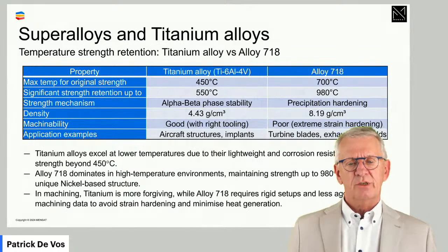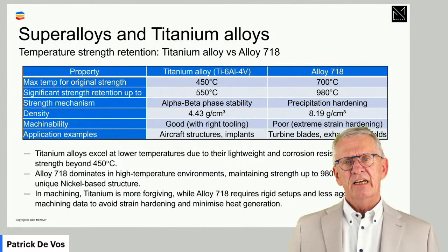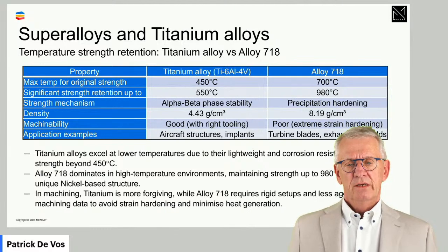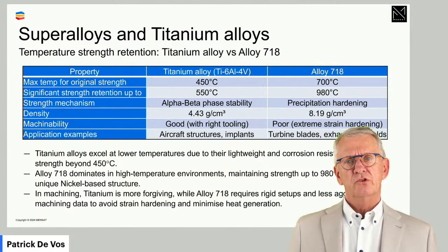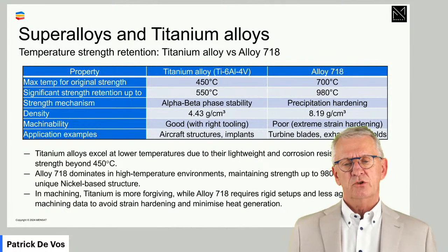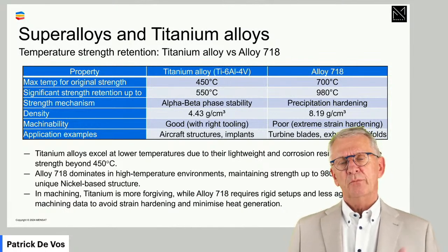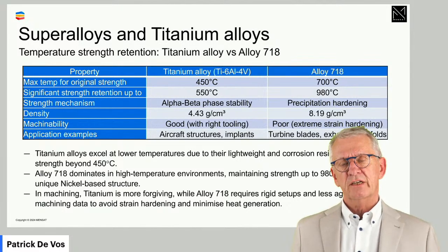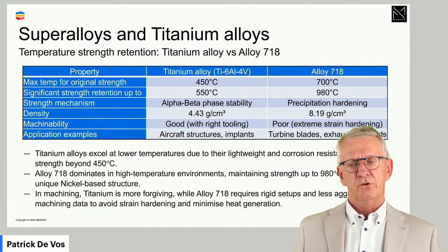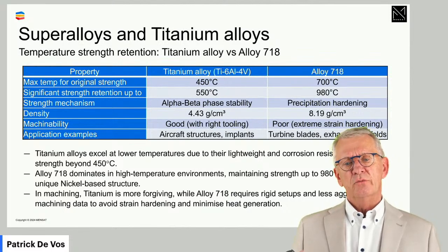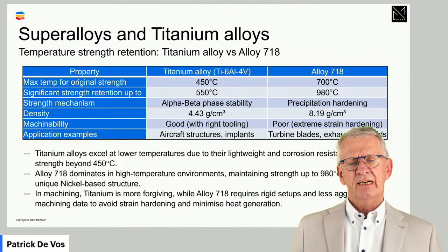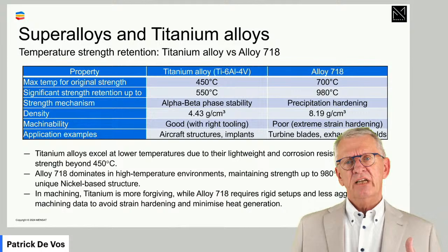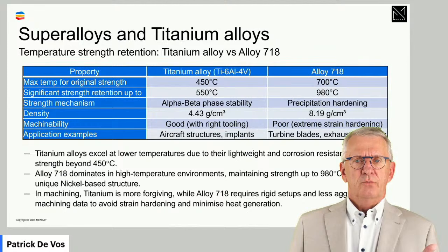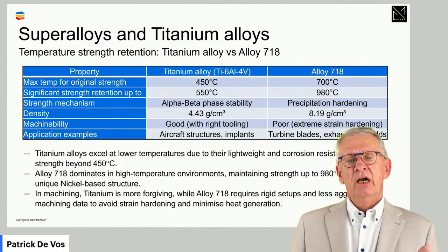Now we have to be careful with that, because if I take titanium alloys and superalloys, and I take here two very typical representatives of those materials, it's titanium 6Al4V, which is commercially perhaps the most used titanium alloy, and I compare it with the superalloy Inconel 718, or perhaps for the first time in this presentation I talk about alloy 718. I'm going to explain within a few minutes what that is. And if I compare these two materials, what we see is that from a strength perspective, at lower temperatures, titanium is stronger than a superalloy, than Inconel 718.